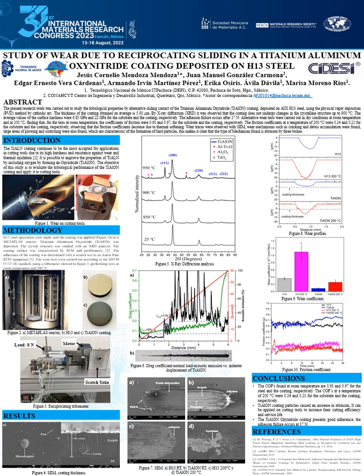Figure 5 shows the X-ray diffraction study. It was found that the coating has a high resistance to temperatures above 900 degrees Celsius. It has a face-centered cubic crystal structure with a lattice parameter of 4.16 angstroms.